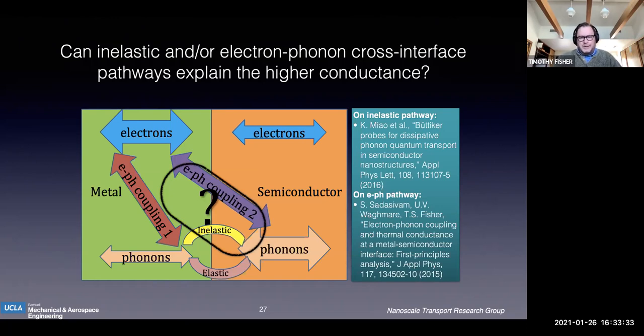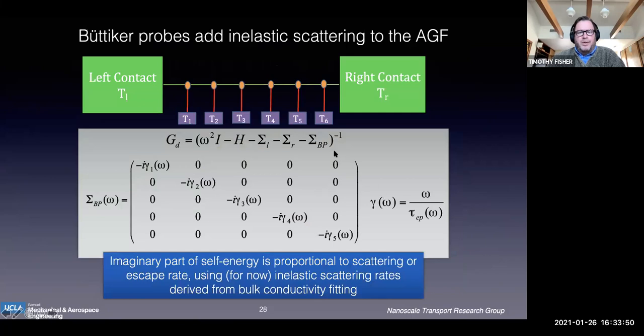There are other sub questions about inelastic and elastic phonon scattering that we had to deal with as well. That's listed on this chart. And if you want to look at how we handled those, some of the papers are listed here. But what we did, and this is important for you to understand, to do multi-carrier DFT, it's not like you just put all the carriers into the computer and just go. You actually have to create coupling elements inside of the atomistic model. So this is a phonon-dominated model, but it's mediated by electron-phonon interactions.